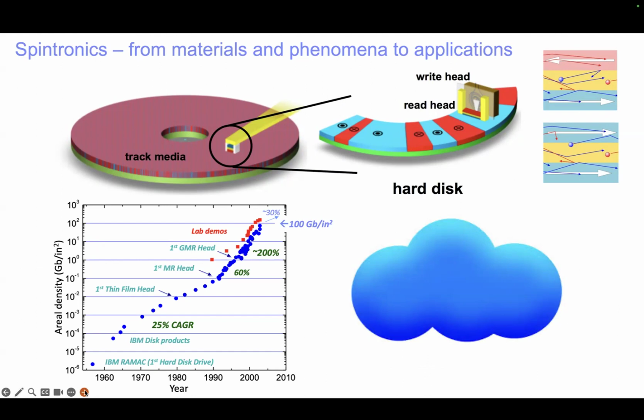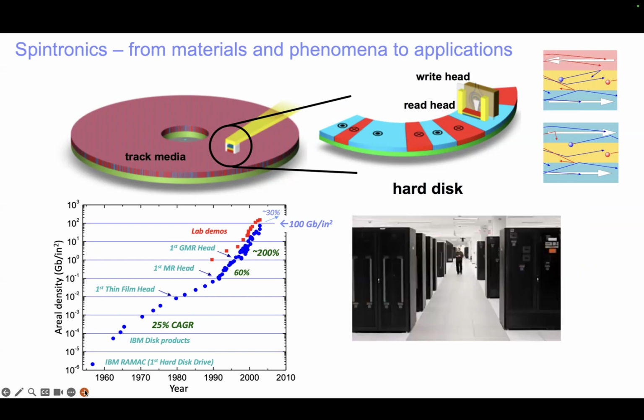This immediately led to rapid increases in the capacity of a magnetic disk drive because this spin valve could detect magnetic regions that were approximately 1,000 times smaller than was previously possible. So it led to a 1,000-fold increase in the storage capacity of these magnetic disk drives in a relatively short period of time. And so this is why essentially we can store all digital data today using magnetic disk drives, but essentially it's this spin valve device that makes it possible. So this is the first basically real implementation of spintronics with huge impact.